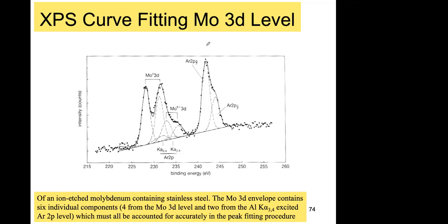So this is sort of looking at the molybdenum 3D level. And this is the molybdenum 0 3D, these two peaks. These are the oxides, 3D molybdenum 6. And then you have argon here because this was sputtered with argon. Although the argon is used to remove layers of your sample, it can also penetrate and stay in your solid, and you will see argon.